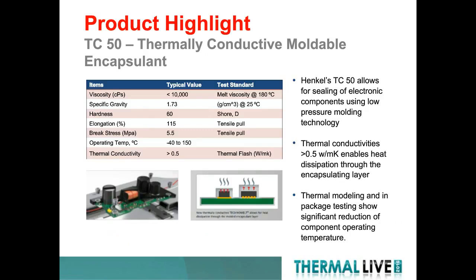Highlighting the performance of this material again, the TC50, or the thermally conductive Technomelt, allows for sealing of electronic components using the low-pressure molding technology. Thermal conductivity is greater than half a watt per meter-kelvin, which enables heat dissipation through the encapsulating layer. We've done significant thermal modeling and in-package testing, which shows significant reduction of component operating temperatures. And we'll go into that in the next couple of slides.